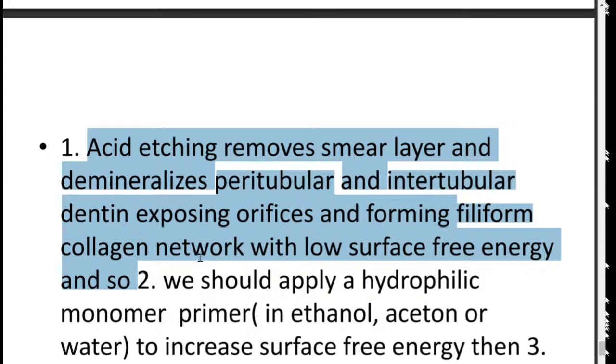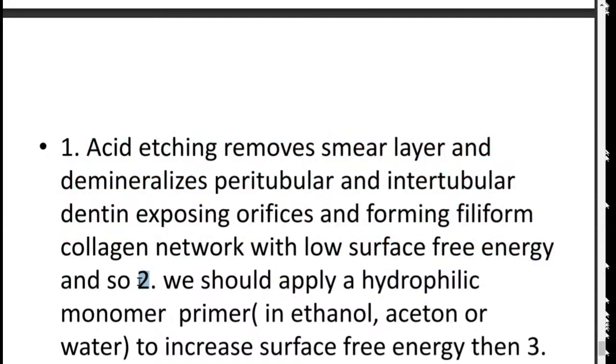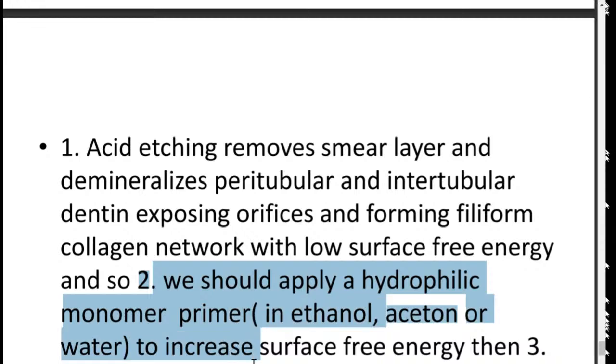First is acid etching, which removes the smear layer and demineralizes peritubular and intertubular dentin, exposing the orifices and forming filiform collagen network with low surface free energy.